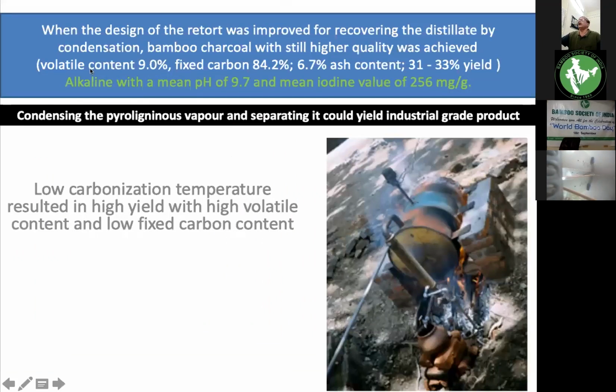When the design of the retort was improved for recovering the distillate by condensation, bamboo charcoal of still higher quality was achieved. That is a volatile content of about 9%, fixed carbon content of about 84.2%, ash content of about 6.7%, and up to 33% yield. Here also it was alkaline, with a mean pH of around 9.7 and a mean iodine value of about 256 milligram per gram, which is of course low. So condensing the pyroligneous vapor and separating it could yield an industrial grade product.